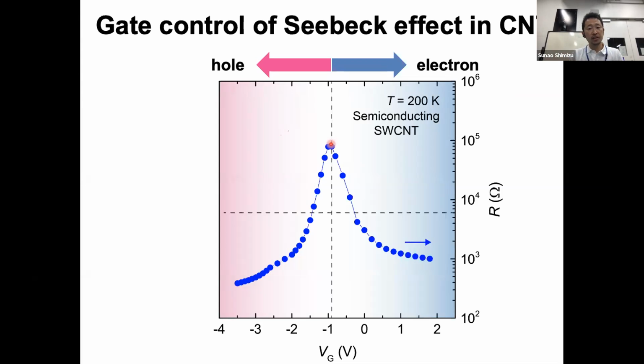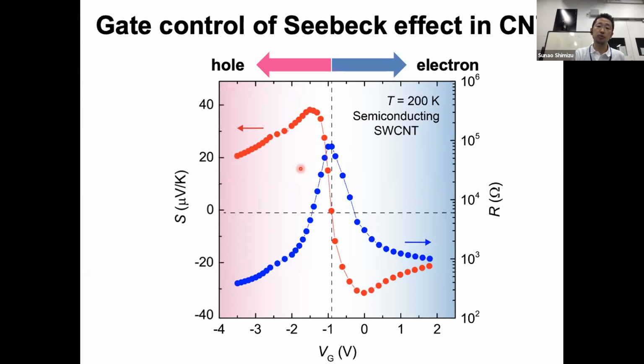We also measured the Seebeck effect simultaneously. The result is like this. In the hole doped region, the Seebeck coefficient is positive, and in the electron doped region, the Seebeck coefficient is negative. And please note that here at the charge neutral point, the Seebeck coefficient is 0 because the contributions from holes and electrons cancel out completely.